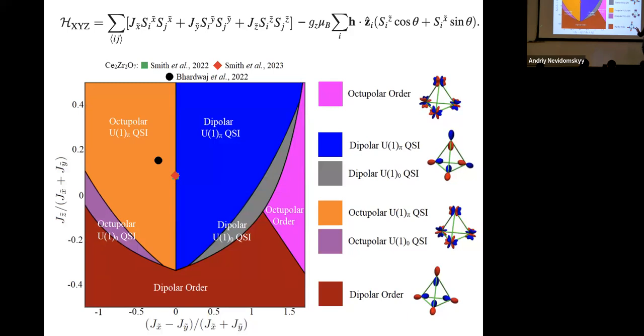So do you expect the pinch point in both cases? You have to do the calculations to see, but certainly any variation like this, the changes in the diffuse scattering will be minor. Things vary, but the big variations are when you cross into a disordered state. But yeah, we're sort of in agreement that the cerium compound is not in the ordered state.